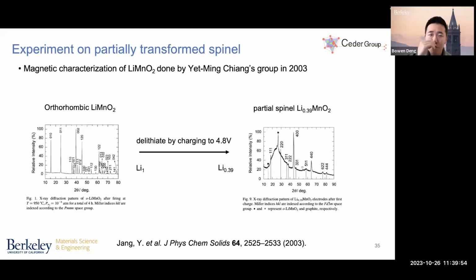However, in 2003, Yet-Ming Chiang's group from MIT performed a magnetic characterization experiment on this partially transformed lithium manganese oxide. So here's what they did. They started with the lithium manganese oxide orthorhombic cell, and they delithiated it by charging to 4.8 volts, which essentially removes more than half of the lithium to form a Li0.39MnO2 partial spinel structure. And these are the XRD characterizations they performed with these structures, where you can see again the decrease of the 15 degree peak and the increase of the 18 degree peak.